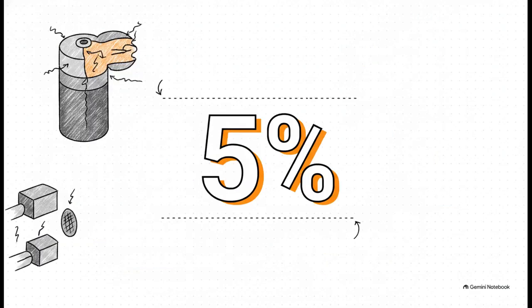Now, moving from the composite wrap to the internal steel components, the standard gets even stricter. Get this, the actual tensile strength cannot exceed the expected value by more than 5% on samples tested for sulfide stress cracking resistance. Now, you might be thinking, wait, isn't stronger steel a good thing?